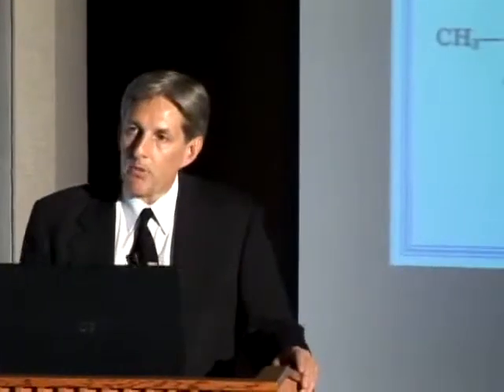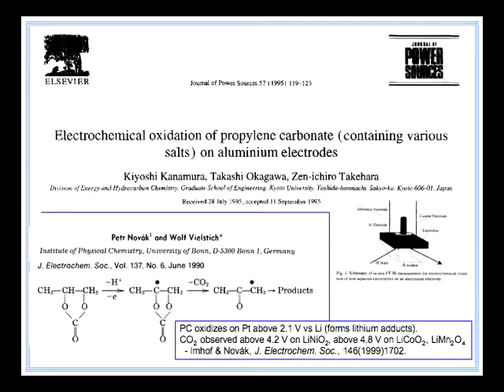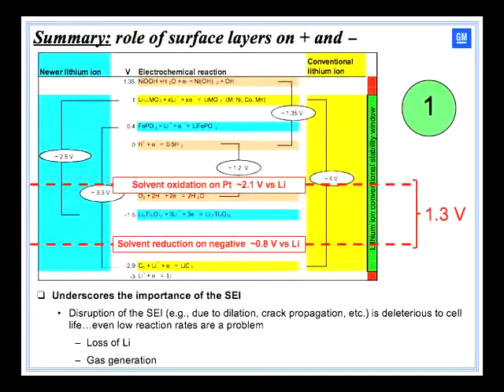It turns out there's a layered structure to this SEI. The inner layer appears to be a very compact lithium carbonate region, and the outer layer is a more gelatinous, amorphous lithium adducts layer. TEM looks at the initial lithium carbonate, and AFM in tapping mode can scrape off a bit of the layer to get the total thickness — about 20 nanometers. These are protective layers. At the positive electrode, similar phenomena occur, though less well-studied. If you subtract the voltages at which these reactions would otherwise occur on each electrode, you get a much smaller battery voltage — underscoring the importance of the solid electrolyte interface.